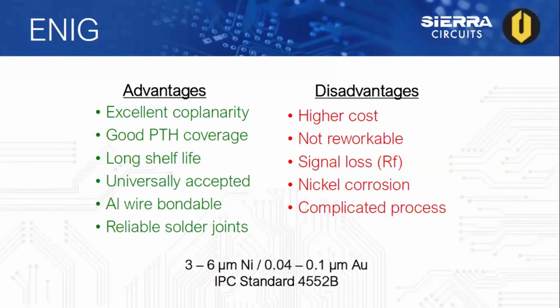This particular IPC 4552B states that you should be between 3 and 6 micron of nickel and 0.04 to 0.1 microns of gold.